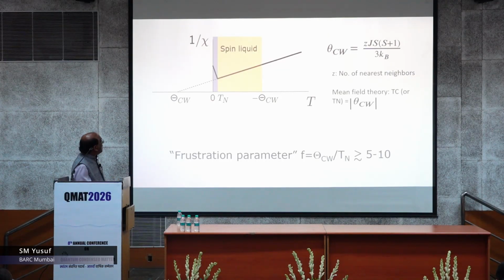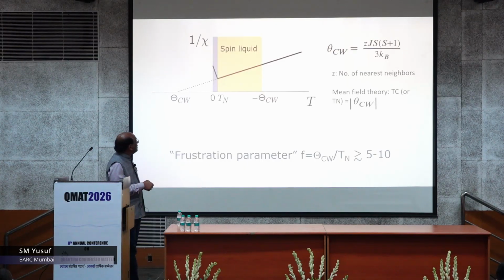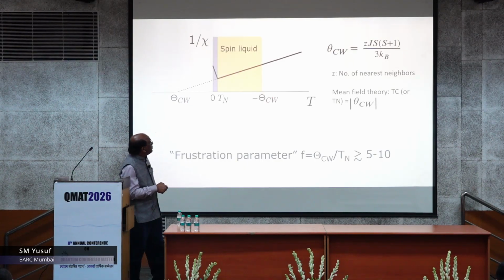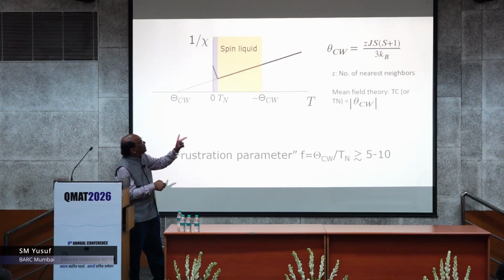Now, when you measure the susceptibility, and take its reciprocal, as I said, this theta, the Curie-Weiss temperature, is proportional to J. J is nothing but the exchange constant. So that tells you the exchange constant between the spins. This is the measure of the strength.